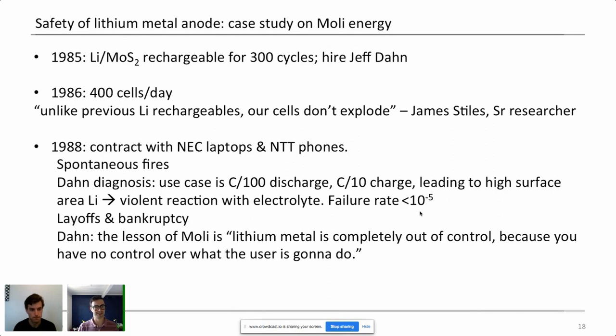And Jeff Dahn's takeaway from that is that he said the lesson of Moli Energy is that lithium metal is completely out of control. You have no control over what the user is going to do. So unfortunately, the user was using it differently than they had tested in lab. They tested, in retrospect, what was the easiest use case to fulfill, with the least likely for lithium to grow in these high surface area structures. And the use case was the worst use case out in the field. So that really set back lithium metal cells.